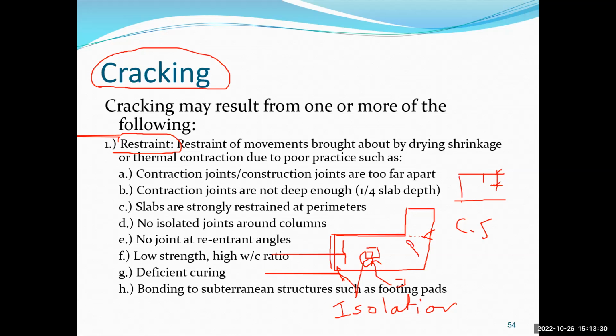If this is H, we cut it H/4, right? And it will eventually crack like this. And so at the top, you see a clean, nice cut, and that's how we control the cracks in this case. The slabs are strongly constrained at the perimeters. That's what we talk about here, and we have no isolation joints around the column. That's what we talk about here, and low strength and deficiency.